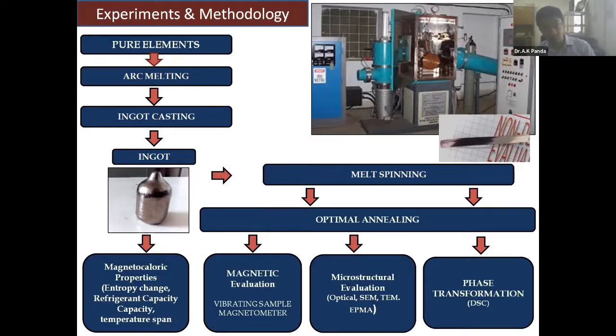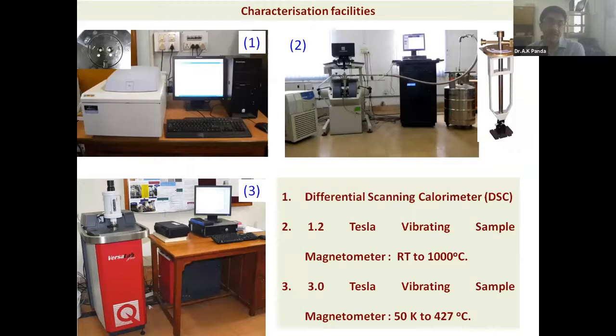And of course, we go for optimal annealing as per the need, and we go for magnetocaloric property evaluation, entropy, refrigerant capacity, and for that you use a VSM, vibrating sample magnetometer. For microstructure evaluation, you all know that we can go for optical, SEM, TEM, and then electron probe microscopy. And for phase transformation, one of the most important equipment required for evaluation of thermal changes in the material is differential scanning calorimetry. We also have a room temperature VSM and a high temperature VSM, up to 3 Tesla, for magnetization studies.